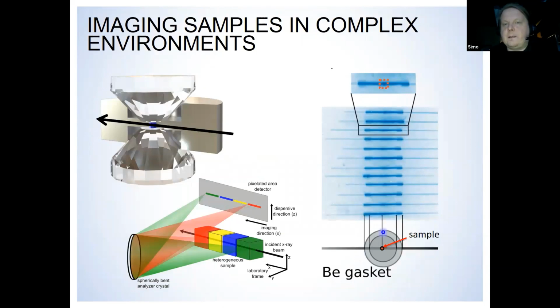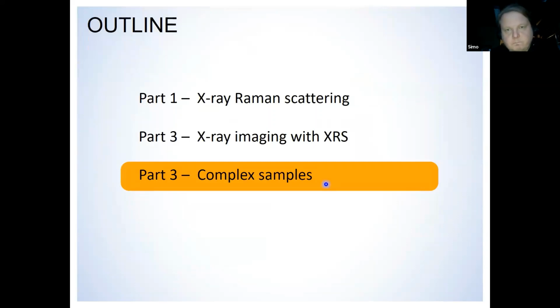I don't know if you can see it very clearly, but these are typical images of this pencil beam going through the system. There's a little increased intensity here, which is the sample, and then we can simply not focus at all on the analysis of the part that comes from the other parts of the cell than the sample. So that gets rid of spurious reflections and other things from the other parts. That was a very brief introduction of how we do the imaging, and then I would show some examples of the samples.